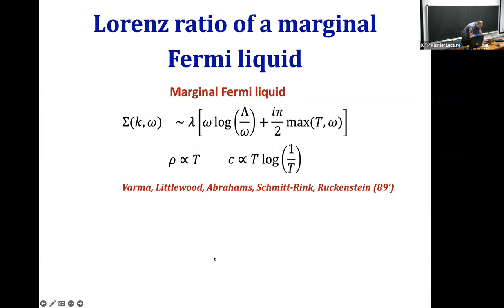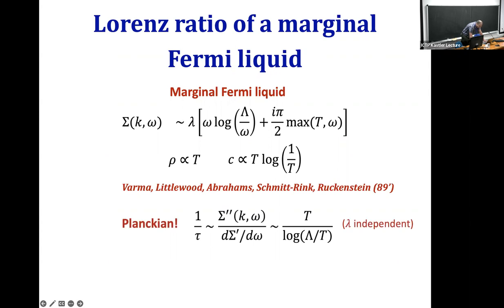Second, it's kind of interesting to note that the marginal Fermi liquid has a nice property. If you look at the single particle scattering rate, that's the imaginary part of the self-energy divided by the derivative of the real part, the Z factor. From the coupling constant lambda, if lambda is big, it actually drops out. This is T over log T. So, if you like, this is a Planckian behavior. It's bounded by k_B T over h-bar. It never exceeds that value. So that's a worthwhile property.